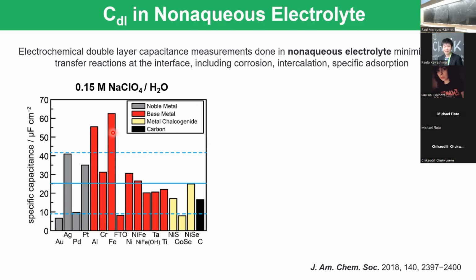And the reason why this is wrong is because, for instance, if you use, I don't know, maybe palladium, the value is around 10. So you can just use that value and that's it. But some people, when they synthesize specific materials, assume that the value is around this average here. They say, okay, I am not synthesizing nickel sulfide, I synthesize nickel phosphide, but I think the average is around 30 or 25, so I can use that value instead. And as I told you, if you know this value and your double layer capacitance, you can get the surface area.